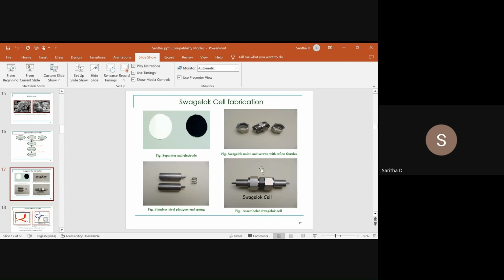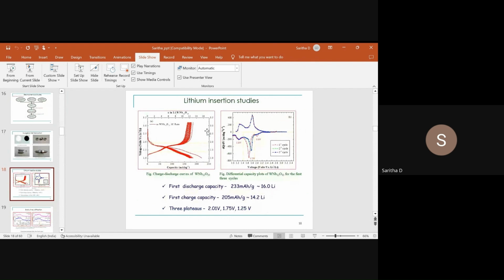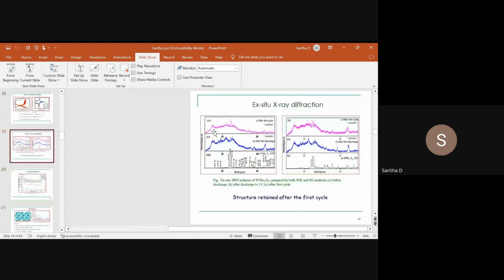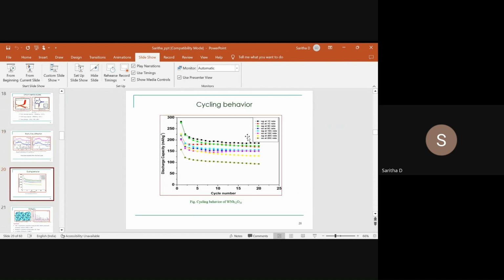This is the unit we are going to test for electrochemical studies, and these are the separator and electrodes, and the maintenance of that. Then the first discharge you can see here is 233, and the first charge is 205. Depending upon the type of material, these will vary based on the redox couples of tungsten and niobium. This XRD confirms what is happening in the material after cycling. It shows that even after several cycles, the structure is retained. That is the beauty of these structures.